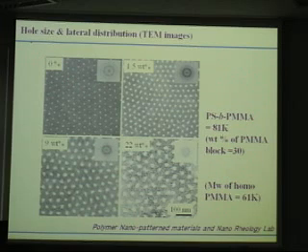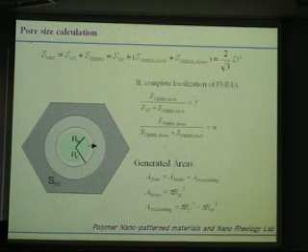But if we put in 1.5% of homopolymer, then the nanohole size increases, then 9%, 22% increase. Also, one clue is that these rings should be very circular, which means the homopolymers or holes will be located at the center of the block.